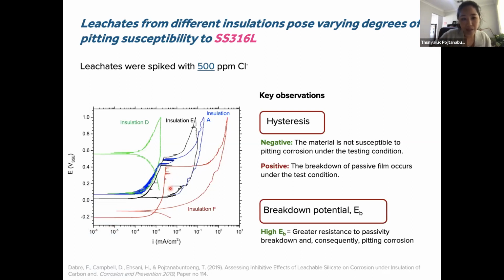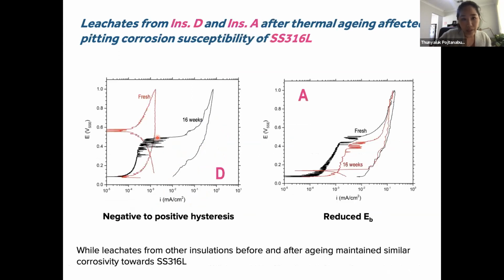And there are a few other characteristics that we could obtain also from the graph. But the highlight from this slide is to show that different types of insulation material will provide different pitting susceptibility. So when we increase the thermal aging of the material, here in the case of insulation D, when it was fresh insulation, there was no hysteresis found. So the breakdown potential was not obtained.